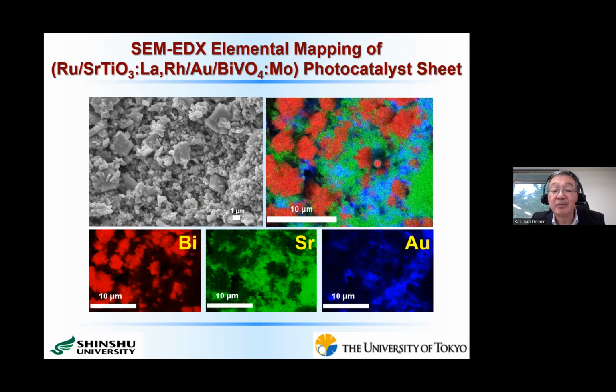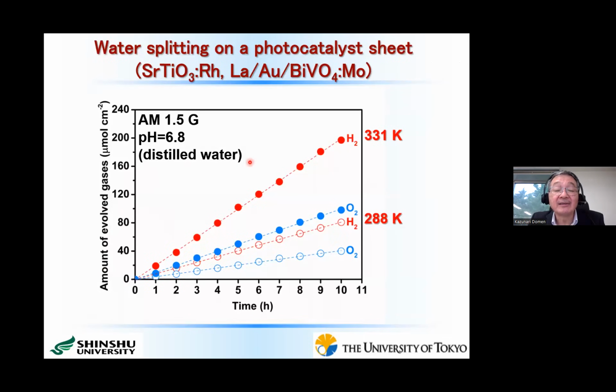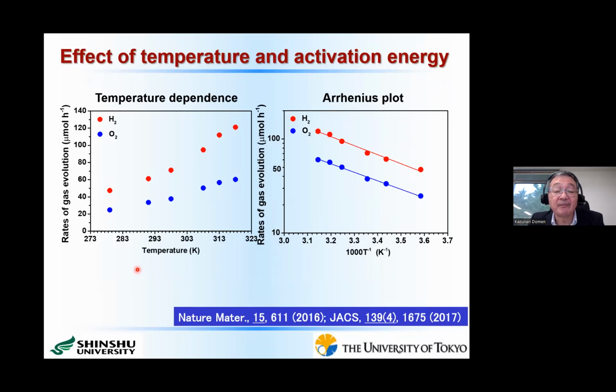But when we put this photocatalyst sheet in an aqueous solution, just distilled water without any electrolyte, and irradiate by solar simulator AM 1.5G, you see that both hydrogen and oxygen evolution take place exactly in a 2:1 ratio, in this case for 10 hours. Another interesting point is that when we change the reaction temperature, the activity changes very much. So we measured the temperature dependence of the activity. As you see here, when we increase the reaction temperature, both hydrogen and oxygen evolution rates increased as shown here. And this is the Arrhenius plot of this data.